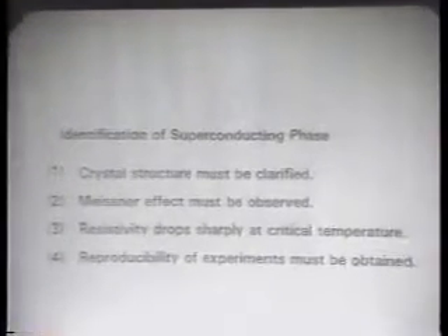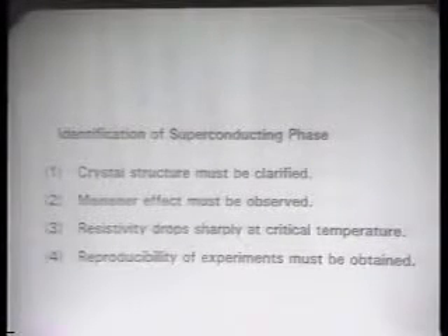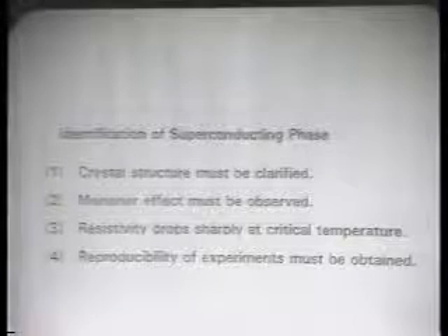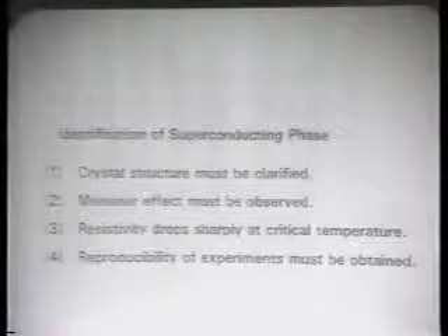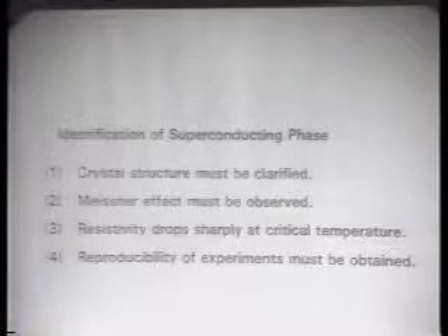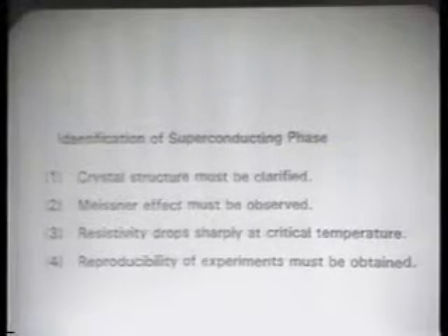The second is a series of materials of lanthanum barium copper O4. Class 2 is lanthanum barium copper oxide, which has a very high critical temperature beyond 90 degrees Kelvin. In order to investigate new superconducting materials, the identification of the superconducting phase is the most important. To identify the superconducting phase, 4 conditions must be satisfied, as shown in the view graph: crystal structure, Meissner effect, resistivity dropping sharply, and reproducibility of experimental results.